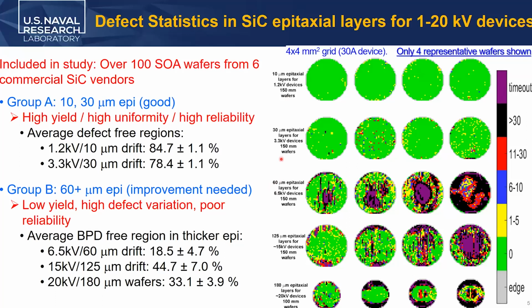We have automatic defect counting mechanisms here, and we see that for the low voltage class, it's very reliable, but as soon as you go to higher voltage class, the reliability tanks significantly. And this is about 6 kilovolt devices, the reliability tanks a lot. So we are trying to figure it out. Also in this 3 kilovolt range, this is actually a very important voltage class, because you can make them and then derate them however you want to get high voltage applications. So we focused on these devices more.